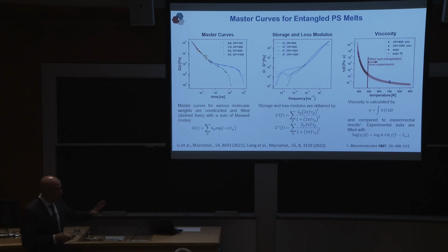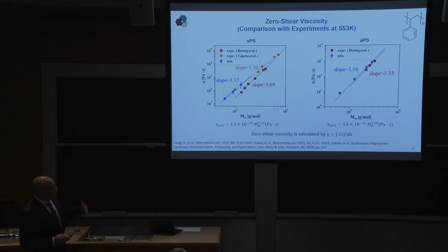So at least we have a model that allows us to go back and forth between the two. Once you get these curves, you can integrate them and get the viscosity. And you can start making comparisons to experiments. So this is data. Experiments are these red symbols for polystyrene. And then the lines are fits to this theory and the predictions, and they seem to agree with each other. There's more data for different tacticities of polystyrene, different experiments by different groups. And you see that in general, the predictions and the experiments agree with each other.